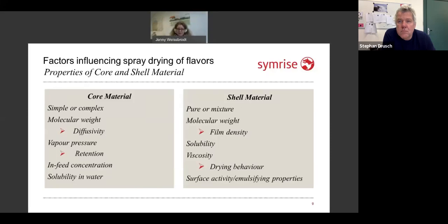What about the molecular weight? Because this directly influences the diffusivity of your component within the matrix, during the drying, but even afterwards during the shelf life of your product. Then the vapor pressure, of course, because drying processes use heat. And of course, the vapor pressure of your component plays an important role concerning the retention. Then the in-feed concentration, how much will you load your particle with your active? And then the solubility in water, because the mechanism of transportation of your active within the drying droplet is very much dependent on if it's water soluble or not.